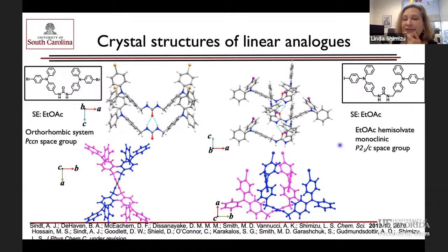And then here's our last one with the iodides here. This one adopts a different structure. So if you look at one of the monomers, here's the monomer in pink, it's U-shaped. It assembles by the urea hydrogen bonds, but this is a little bit longer, so they're weaker because there's also additional iodine pi interactions, so halogen bonding interactions that help organize this into the crystalline structure.